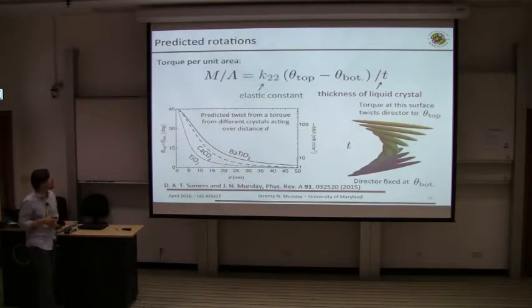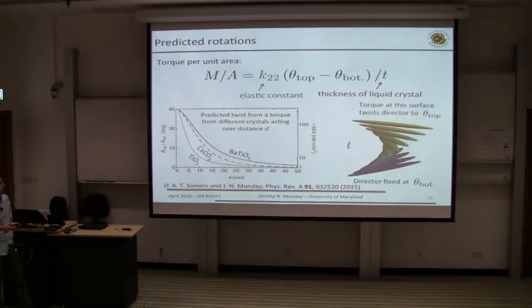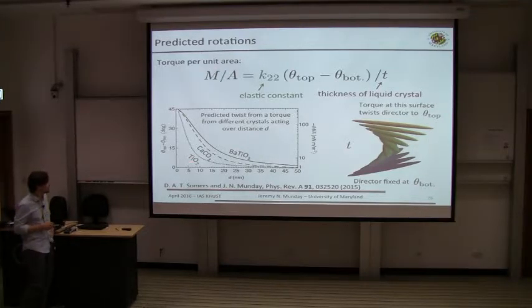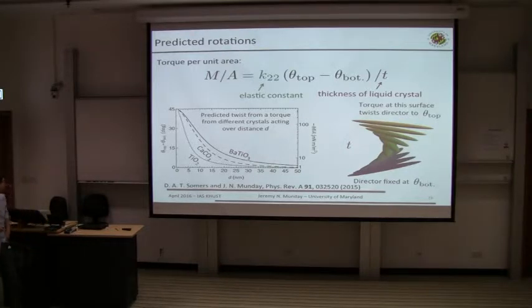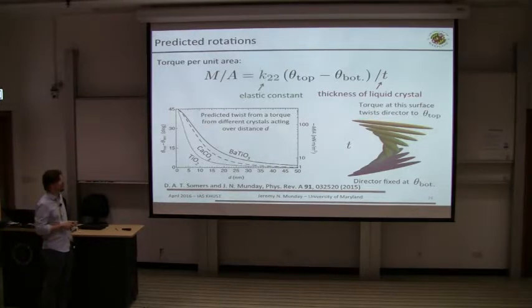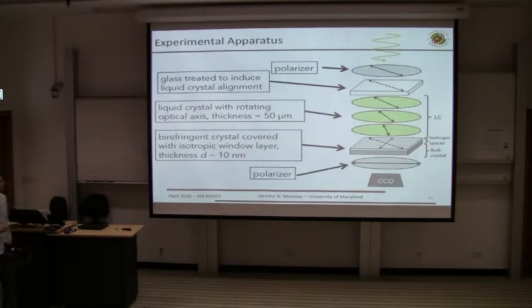And so we can take a look at this again for some typical numbers here and look at how much the liquid crystal would rotate going through this bulk liquid crystal, given various values that we might calculate for the Casimir torque based on different combinations of birefringent materials with different layers of a spacer layer here. And so you can see basically on the order of several degrees rotation over tens of nanometers of separation for all these materials. And so we were putting together an experiment for this.